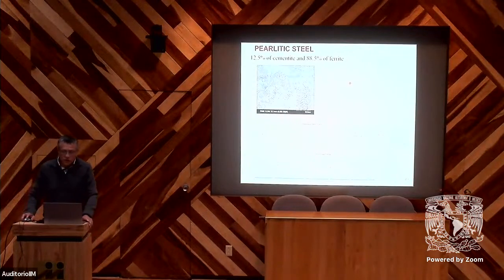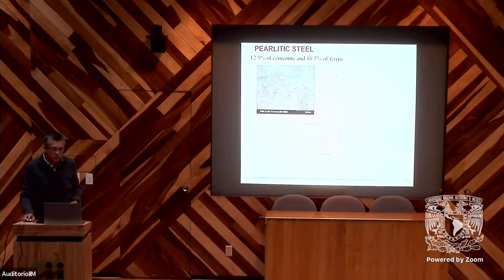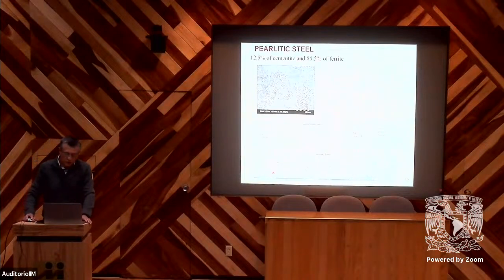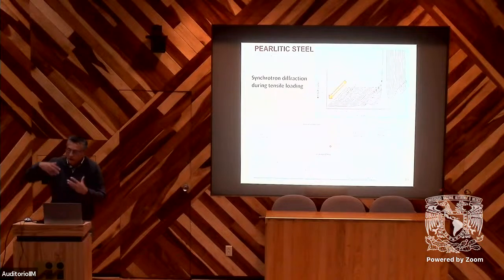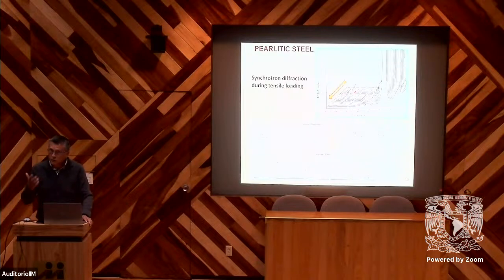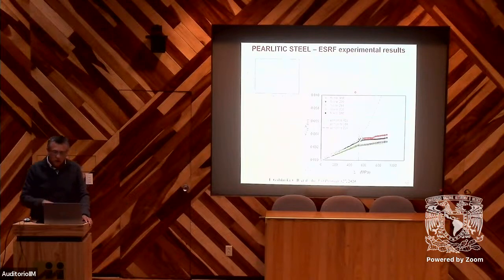So using this high intensity of synchrotron, we have in the spectrum here the different peaks of the ferrite, and we have a relatively low intensity for cementite. And if we make a magnification, we can see that the peaks of the cementite can be treated. So if we apply the fit, we can see the evolution of the peaks and the displacement of the peaks for the cementite. That means we can now get the behavior during the in situ test of the diffraction of the different reflections for the ferrite and for the cementite.